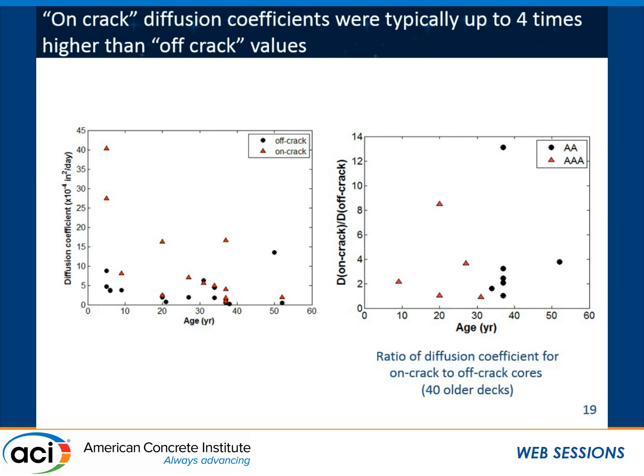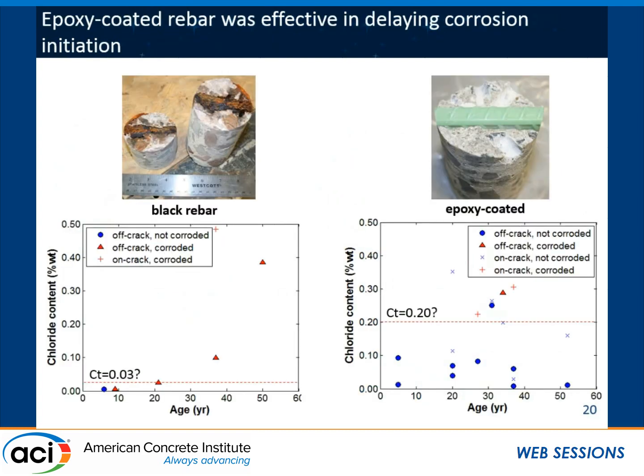For these, we also figured out a ratio of the on-crack to off-crack. We see that for most decks, that ratio is somewhere between 1 and 4. So it looks like the cracking can accelerate the diffusion by up to a factor of 4. Okay. We also looked at the black rebar and epoxy-coated rebar, again, in cracked decks. All of the red dots show that the rebar has started to corrode. The blue shows no corrosion. It looks like at a chloride content of about 0.03% of the concrete weight, the black rebar started to corrode. And for the epoxy-coated rebar, it looked like that corrosion threshold was increased by a factor of about 7.